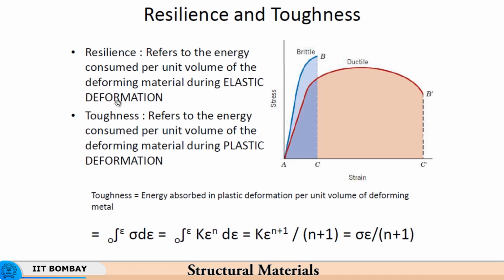plastic strain. So, here up to this strain, let us say this entire area under this curve is the energy per unit volume. Again this is per unit volume, because you see that sigma is force divided by area, d epsilon is dl by L. So, force into dl is the energy divided by A into L. In the denominator you have force divided by area, area and L in the denominator, because you have F upon A and d epsilon is dl by L. So, F dl upon area into L. So, the denominator has got volume as the term. So, that is the reason why this is energy per unit volume.